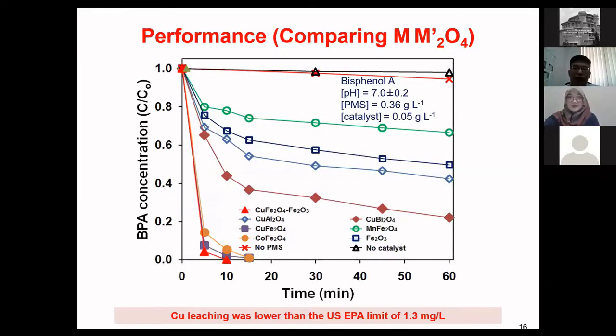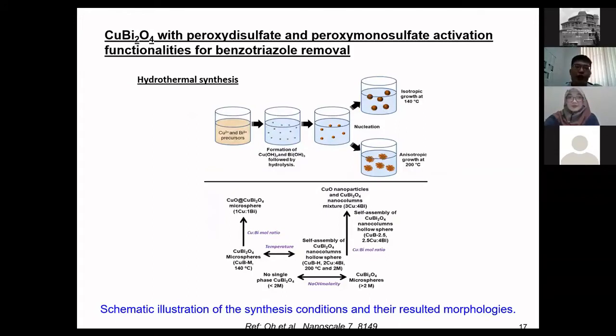So the next way to really improve it further is to look into another type of mixed metal oxide catalyst. We look into copper bismuth oxide. This copper bismuth oxide is also a form of mixed metal oxide. And what is good about this catalyst is that it can be used to activate two different types of oxidant, which means it has some bifunctionality properties. You can use it for PDS, you can use it for PMS. It's quite versatile. If you look at a normal mixed metal oxide catalyst or any single metal oxide catalyst, usually it can only be used to activate one type of oxidant, and it's not reactive to the other one. So for this copper bismuth oxide, you can use it for both PDS and PMS.